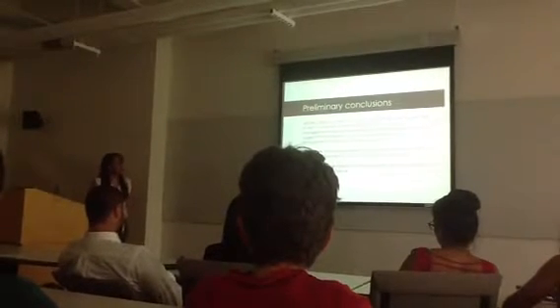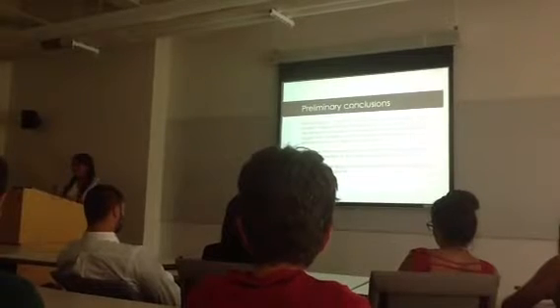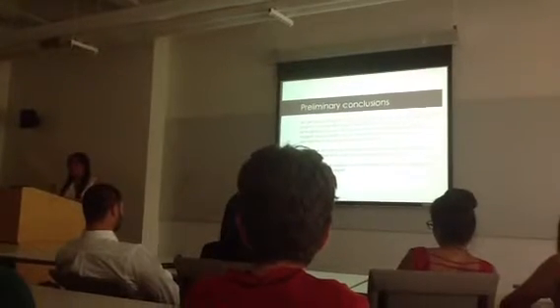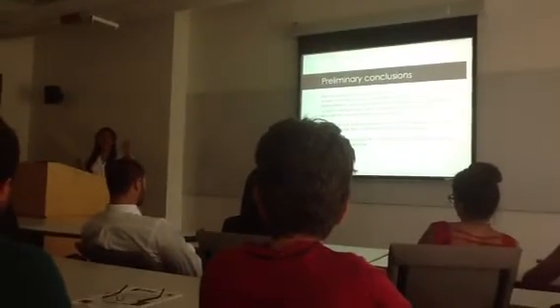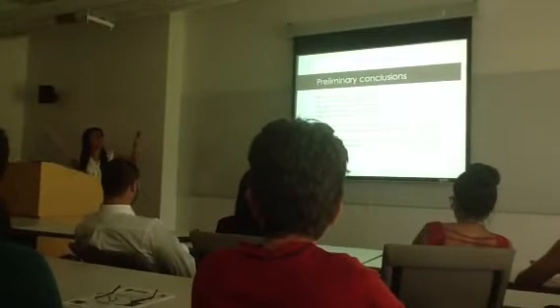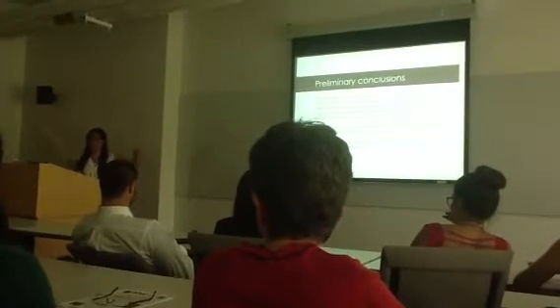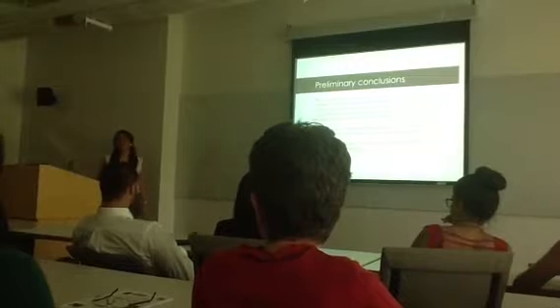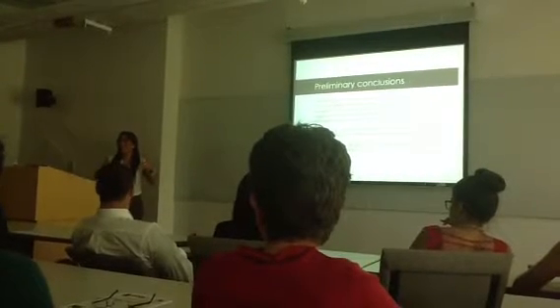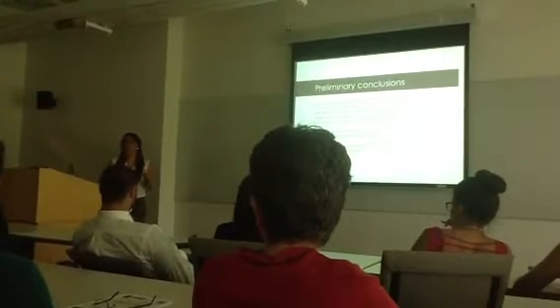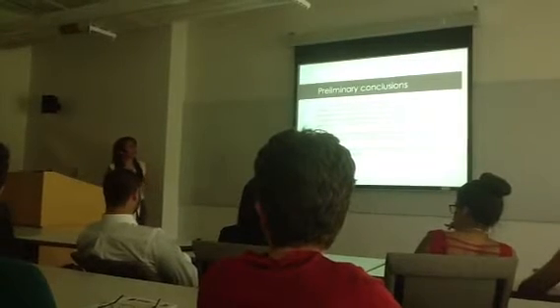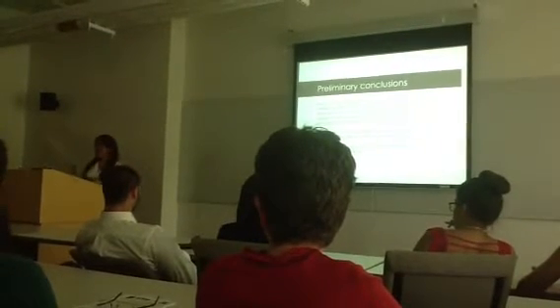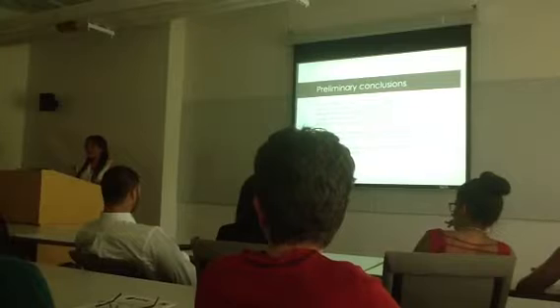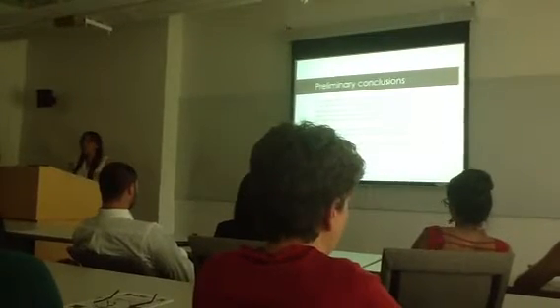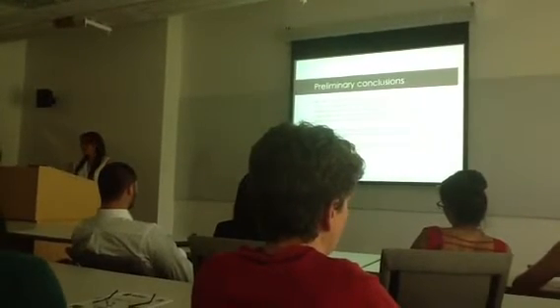So this is one of our preliminary conclusions. And the other one is that, unfortunately, the absolute activity numbers are not as good as the amorphous materials, because in the table with all the triplicates, most of the catalysts don't achieve the current density that correlates with the 10% efficiency. But the good news is that we believe we developed a coherent method for isolating the most active form of the nickel and iron-based perovskites.